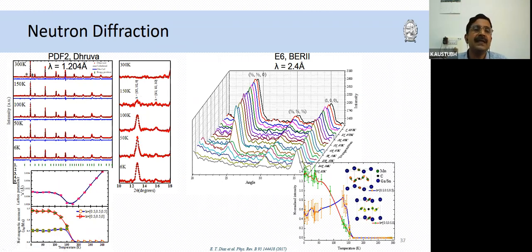order. So we did this experiment at two different reactors. One is in India at Dhruva reactor in BARC, and the second one was in Berlin at E6 beamline at BER2. The reason why we repeated these experiments at BER2 was because of the wavelength. Here, the wavelength was much longer, so we could get a better Q-space resolution to identify the magnetic peaks.